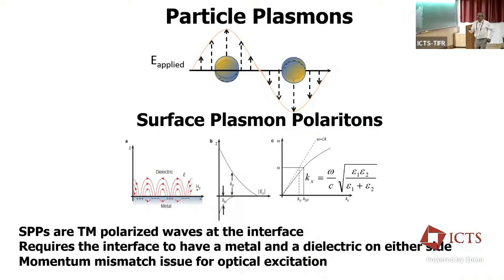So similarly, you can have a metal and a dielectric interface. The free electrons in the metal surface can be excited to have a charge density wave which propagates along this interface. So this is a surface mode, which means that away from the interface, you have these exponentially decaying fields. Compared to the light line, the dispersion of this surface mode is given by this expression, which means that there is a momentum mismatch. So directly by shining light on a metal dielectric interface, we cannot excite these plasmon modes.